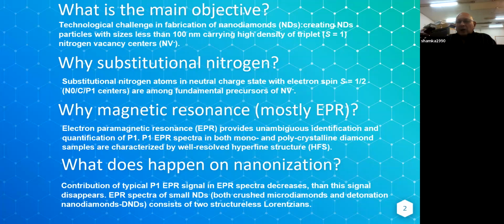P1 EPR spectra in all mono- and polycrystalline diamond samples are characterized by a specific signal with hyperfine structure. It means that the interaction between the unpaired electron and the N14 nuclei provides a very, very clear signature of P1 centers, which consists of 3 main lines. But what happens? Everyone observed it personally or saw the spectra in many, many publications.